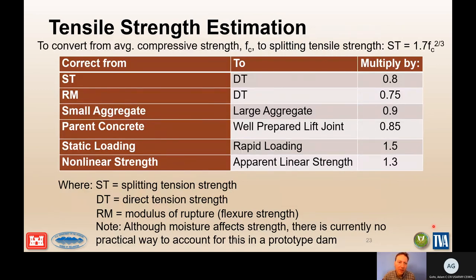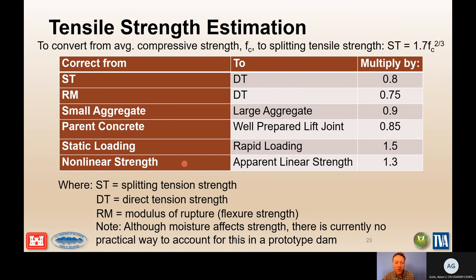This slide summarizes best practices. If starting from compressive strength, use the splitting tension strength correlation from Raphael listed here, then correct to direct tension or modulus of rupture using given multipliers. Corrections include: small to large aggregate, parent concrete to lift joint, static to rapid loading, and non-linear to apparent linear strength. If you have particular test data and need to correct it to something else, you can use these multipliers as well. Consider the specifics of your situation — a well-prepared lift joint uses 0.85; a poorly prepared lift joint should use something lower.